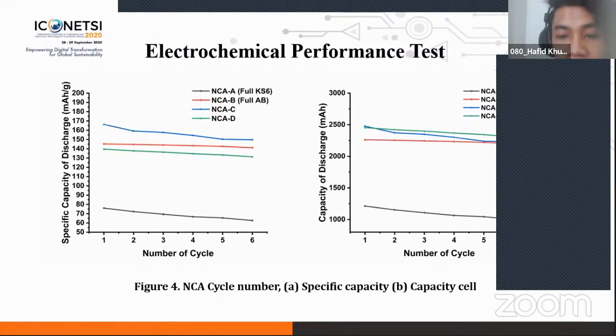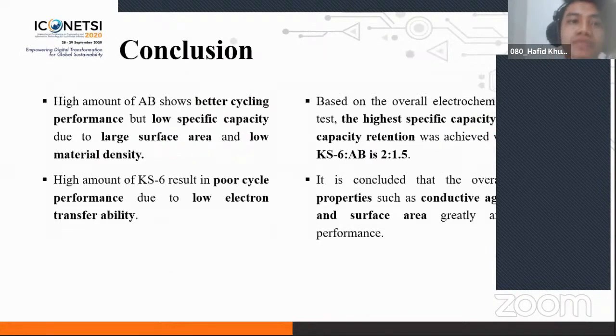However, since AB has low density, the overall cell capacity is lower compared to other samples. Conclusion: a high amount of AB shows better cycling performance, but low specific capacity due to the larger surface area and the low material density. A high amount of KS6 results in poor cycle performance due to the low electron transfer ability. Based on the overall electrochemical performance test, the highest specific capacity and retention was achieved with a KS6 to AB ratio of 2 to 1.5. It is concluded that the overall composition as conductive agent and surface area greatly affect the performance.